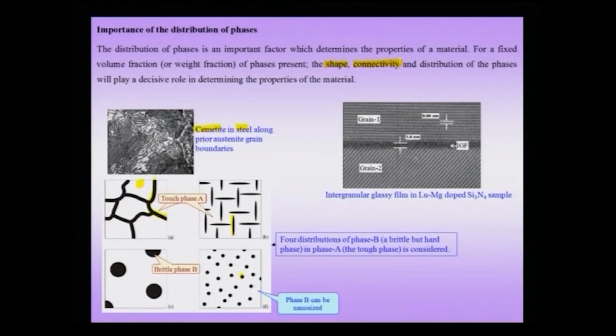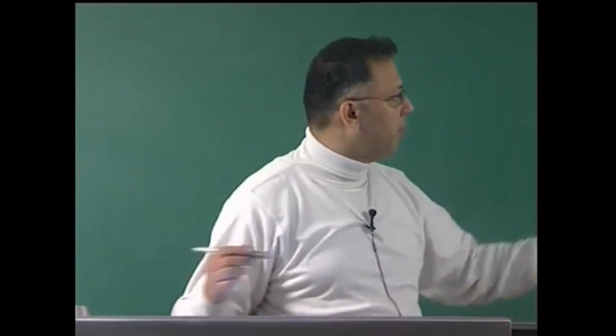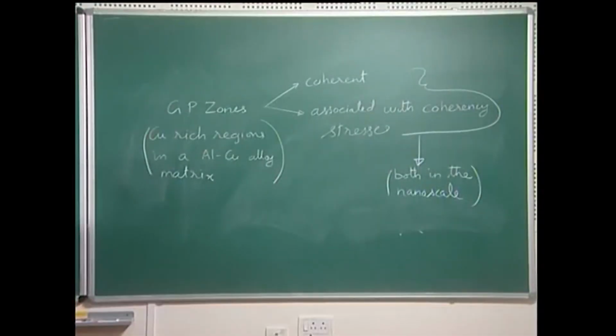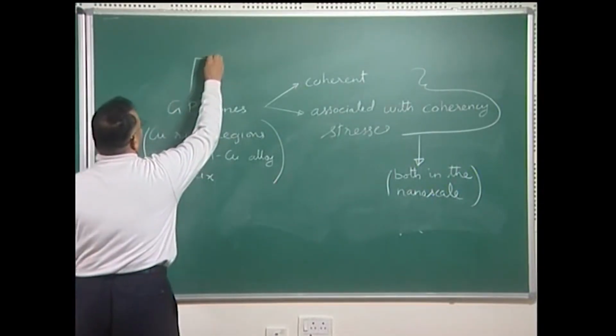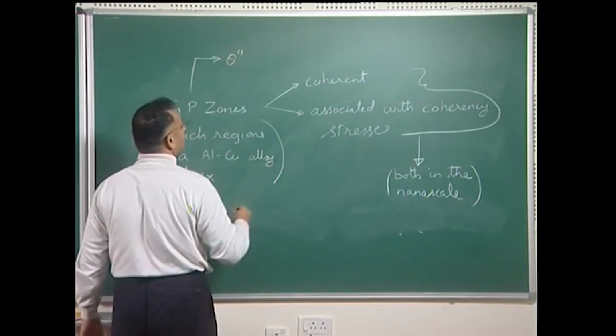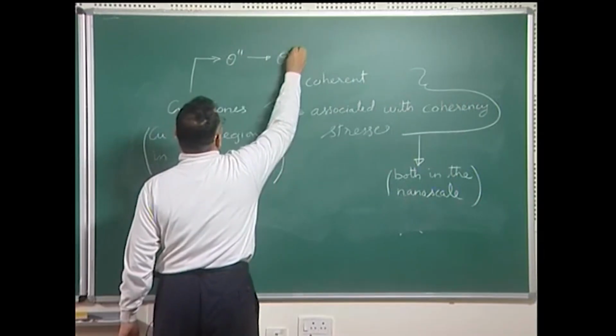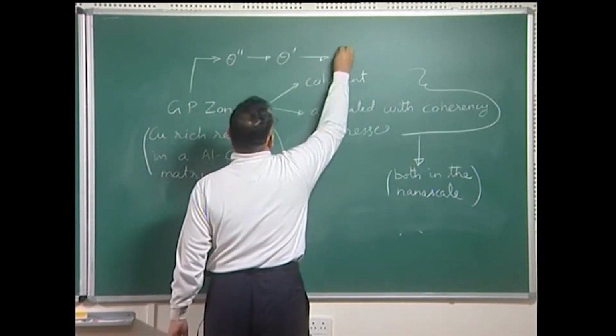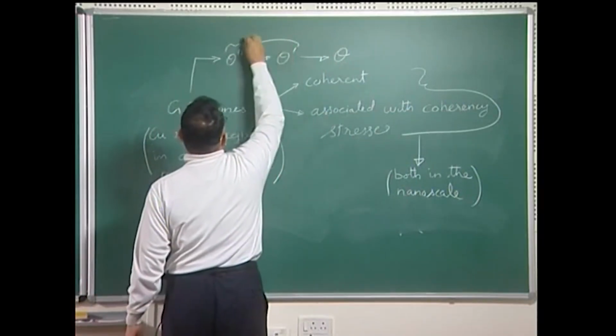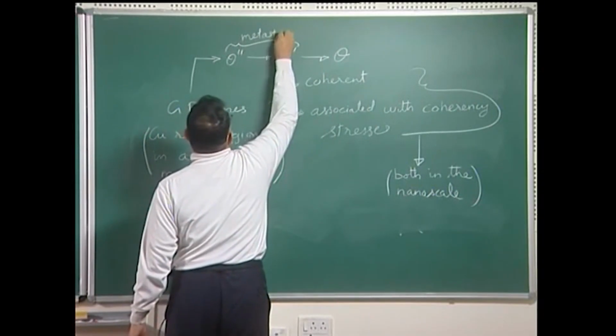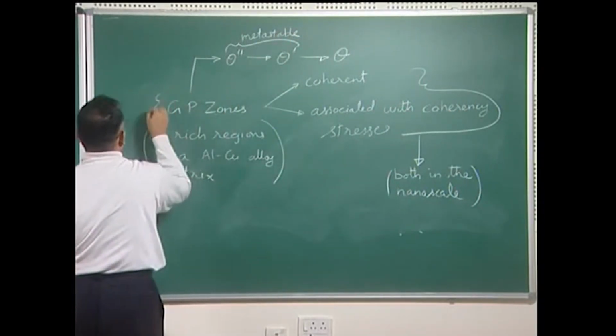Then I need to know the spatial distribution of these phases, and suppose if this microstructure is evolving in time, then I need to know the spatio-temporal evolution of this microstructure. For instance, in the example we just now took of GP zones, if this component which has GP zones is employed in service at high temperatures, then these GP zones will slowly transform into theta double prime precipitates, which will later on transform into theta prime precipitates. Then finally, you will get the equilibrium theta precipitates. These two are metastable phases, and GP zones are metastable as well.